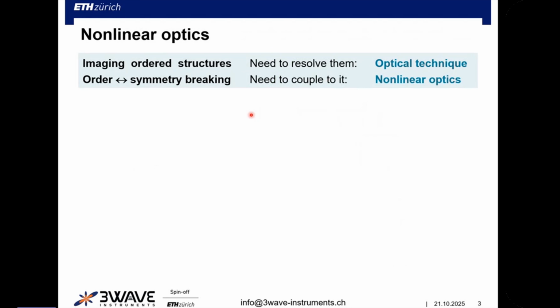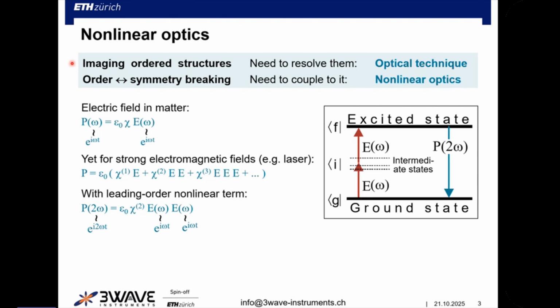And our reasoning was that we said, okay, we want to image ordered structures and their functionality. So imaging implies something optical. So let's think about an optical technique. We also want to see ordered states, symmetry breaking, and what it does in terms of functionality. So something that is very sensitive to symmetries is nonlinear optics. So that was then basically the technique of choice to somehow involve as a new in situ tool. And what we then opted for is what we have been doing here for many, many years, namely nonlinear optics in the form of optical frequency doubling or second harmonic generation.